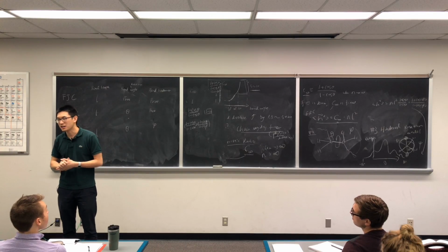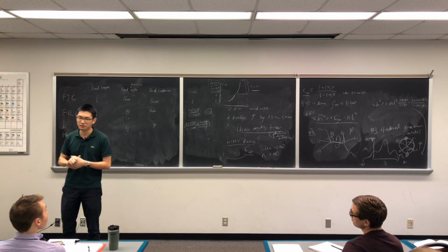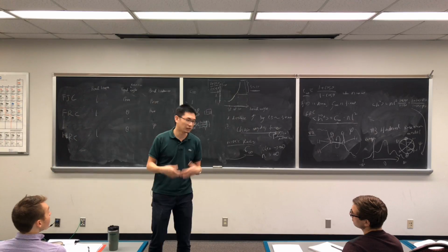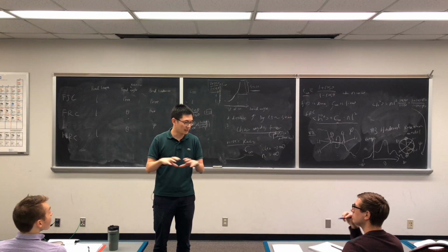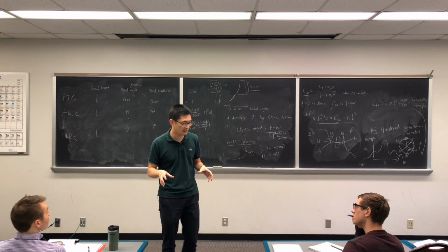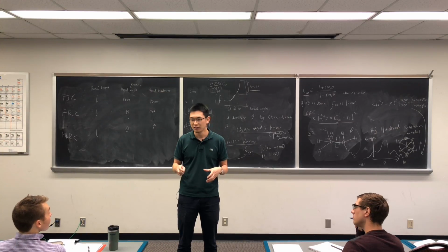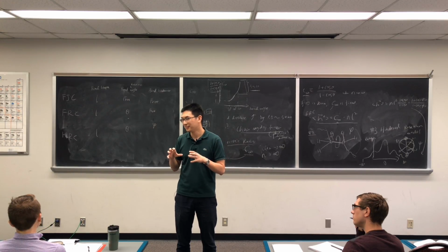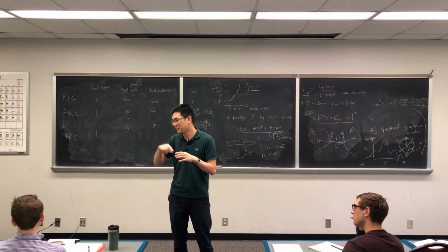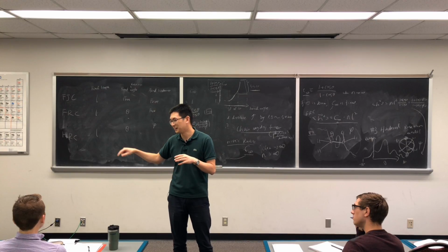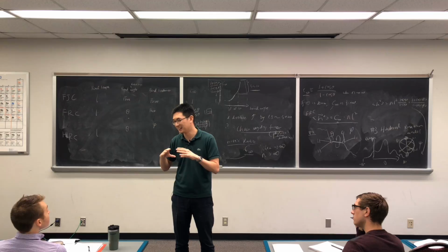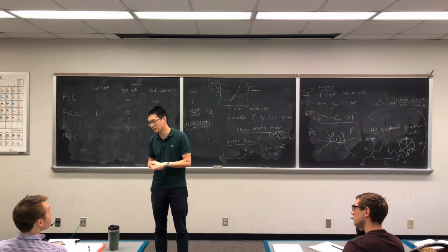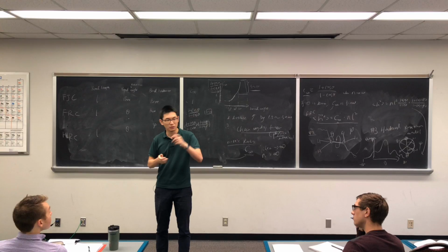worm-like chain models. In that case, for example, if you have a fused ring, like a thiophene unit or a benzene unit in the backbone, that is typically encountered in rod-like chain models, you need a different model to describe it. Because in this case, we assume there's always a bond angle, and the bond angle can rotate. But if you have a fused ring, it's super rigid and rod-like, and the current model does not describe it. And good question.